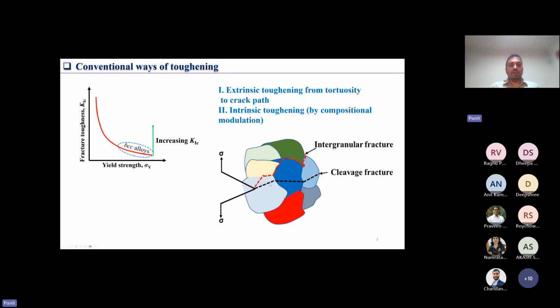Although the improvement in fracture toughness because of these extrinsic mechanisms is not as much as what you can achieve through intrinsic toughening. So in BCC alloys you can also have some intrinsic toughening, by having compositional modulation that can allow defect nucleation or movement of defects. For example, in tungsten, if you add more and more rhenium, you can ductilize tungsten. So those mechanisms also work in improving fracture resistance of BCC materials. But the problem with that is that you will also be affecting the yield strength of these materials.